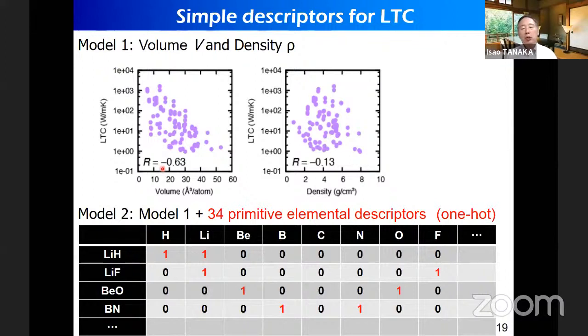And on top of these two quantities, we have used elemental descriptors. As elemental descriptors, of course, there are many different kinds of choices: electronegativities or position in the periodic table, ionic radius, and so on. But instead of using such sophisticated or heuristic quantities, we have chosen very primitive elemental descriptors, which is one-hot expression of the elements. For example, lithium hydride. Hydrogen is here, lithium is here, so we gave 1 to these descriptors. For the rest of the 34 elements, there is no such element included in this compound, so we gave just 0. So there are altogether 34 primitive elemental descriptors plus 2 descriptors here. So we used 36 descriptors.